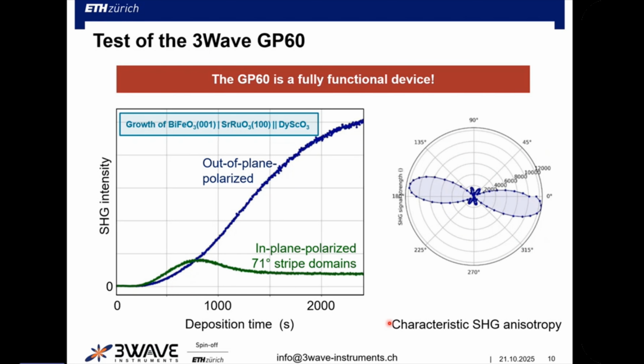Just as my last slide, that this really works. So if we take our shoebox-sized excitation and detection unit, and we apply the same thing to the bismuth ferrite, as before with the big laser system, we see very nicely how you have the emergence with growth time, in this case, of an out-of-plane and an in-plane polarized contribution to the bismuth ferrite polarization. You have a very neat, almost noise-free polarization analysis that tells you how it grows. So like in stripes, we will come to that afterwards. So it's not just an idea or some prototype or something put together, but it's really a working device that we have in our lab. All right, and with that, I'm done with the scientific part.